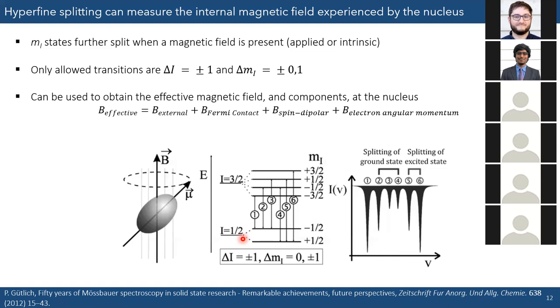And so now there's going to be many, many more transitions that can occur, but they still have to obey these selection rules. And so there's actually going to be six different transitions that can occur, all with different probabilities of occurring, which is going to give us a rather complicated spectrum. But it'll always give you, for iron, a sextet spectrum because there are six different transitions that can occur. So this splitting here is very analogous to what NMR is based on. So for example, this is really what you'd be looking at for NMR. But now we're also including the excited I equals 3/2 state. So that's how we have so many more of these transitions.